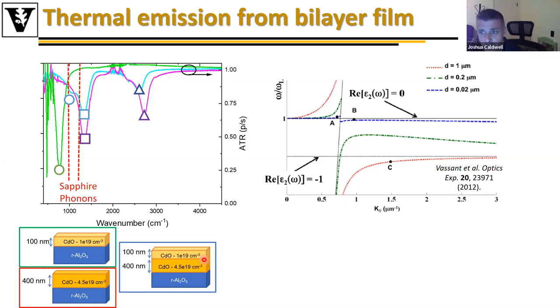Okay, so if you see here, we're actually going to be looking at the Berreman modes in these cases, which are off to the left of the light line. As we have a thicker film, these modes actually have some dispersion to them, and thus they're going to occur at frequencies redshifted from that of the ENZ polariton mode.